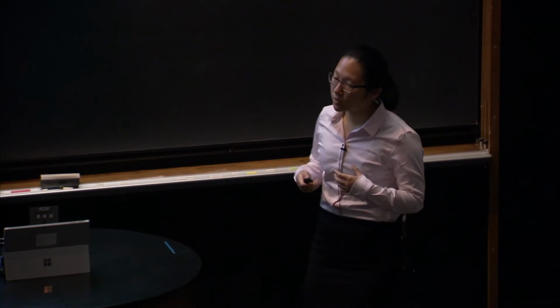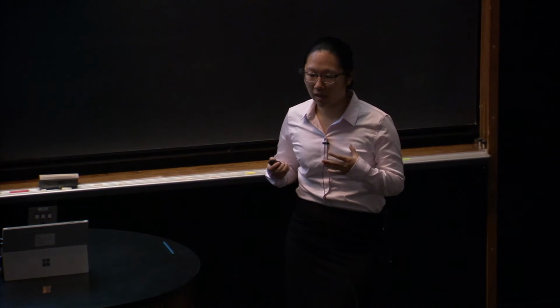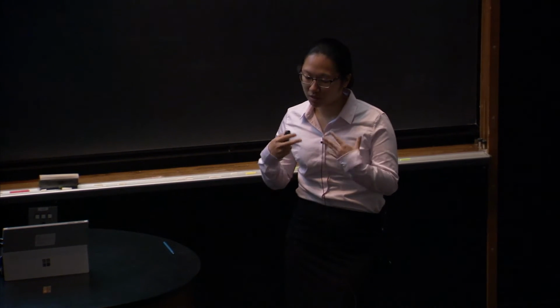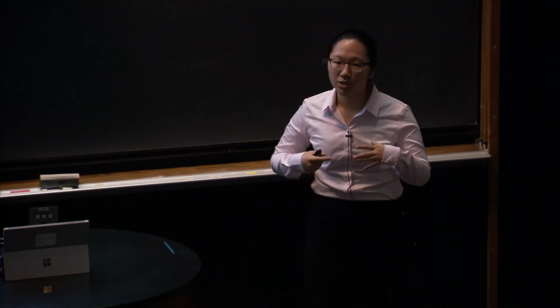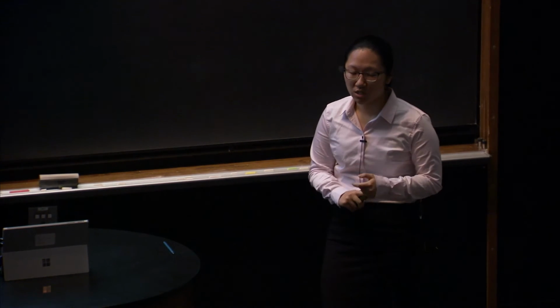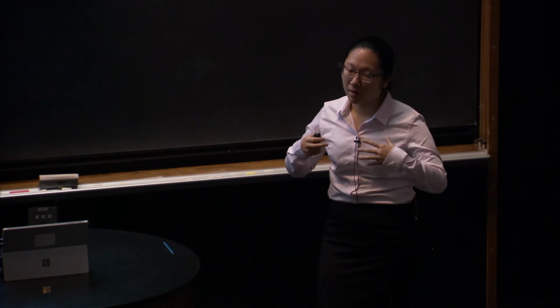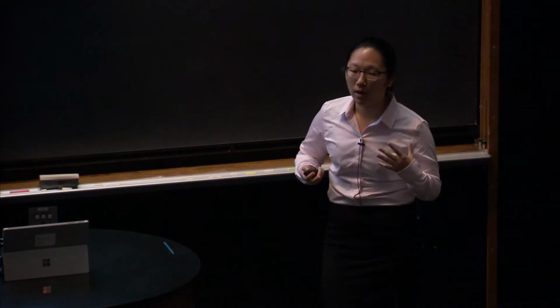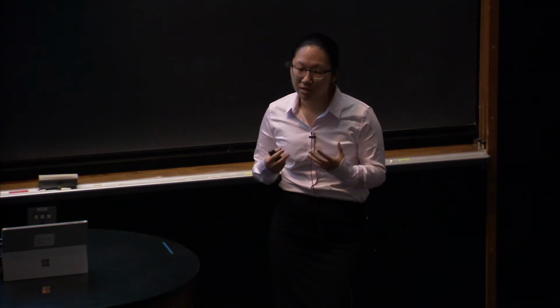So we can further use the Raman spectra of the graphene nanoribbons to analyze how the processing parameters affect the growth. This is done by taking the ratios of the D to G peaks and the 2D to G peaks. The ratio of the D to G peak gives an indicator between samples of how the number of edges has changed, while the ratio of the 2D to G peak gives an indicator of how the thickness of the samples has changed between samples.